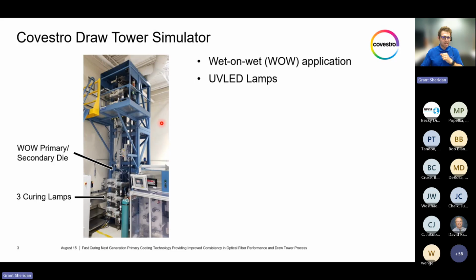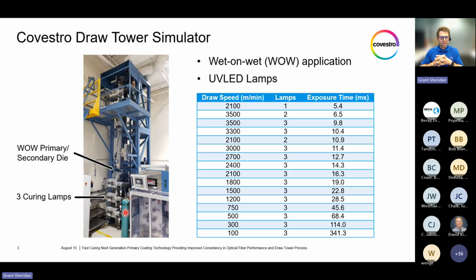For the draw tower simulator, we use metal wire and feed it running down, and then for the wet on wet, the primary and secondary dyes are coated here, and then run through up to 3 curing lamps, or 3 UV LED lamps in this case. With our draw tower simulator, we're able to vary not only the speed, but obviously the number of lamps or lamp power to vary exposure time. So we're able to vary the draw speeds from 100 to 3,500 meters per minute and the number of lamps from 1 to 3 lamps.